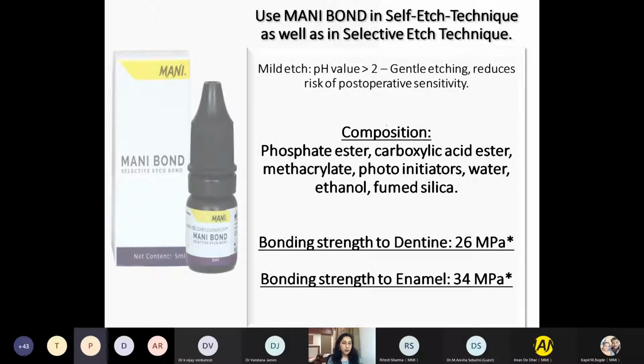And the best part about this bond is that it's a mild etch bond, wherein the pH value is more than 2. So gentle etching also reduces risk of post-operative sensitivity, and such kind of gentle etching bonds can be used safely in deep dentine. The bonding strength to dentine is 26 MPa, and of course the enamel is great. So how does this bond work?